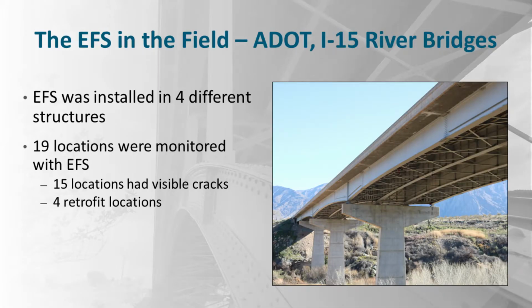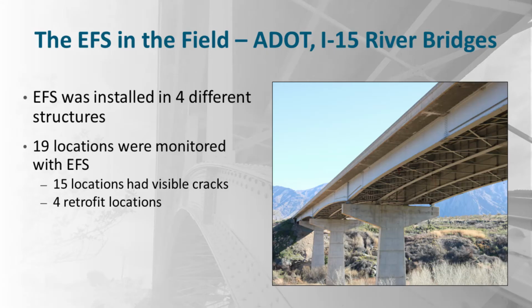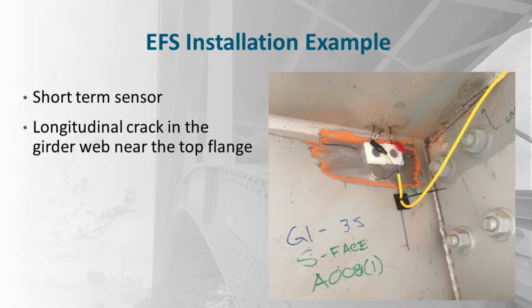The EFS on an actual field. So we have a project in the Arizona DOT in the I-15 river bridges where we actually inspected 4 different structures. And in those 4 different structures, we had 19 locations monitored with the EFS, 15 locations had visible cracks, and 4 retrofit locations were actually inspected as well. These locations were actually selected by the ADOT and the team executing the project.